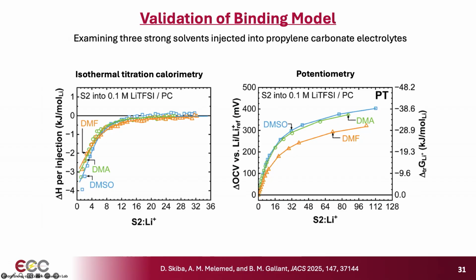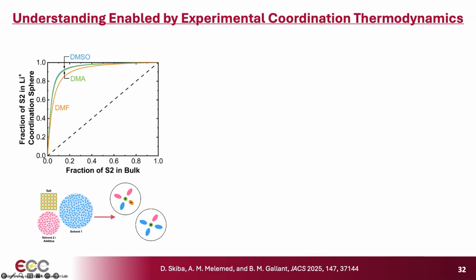Okay. So with some math that's under the hood, we run this model and we're actually able to fit both of our data sets, both the titration data and the OCV data. And the fits are actually quite good, as shown in the solid lines, for 3 different strong solvents, DMSO, DMA, and DMF. Okay. So we're really able to describe these data quite well, and so that lets us unpackage and access the thermodynamic parameters.